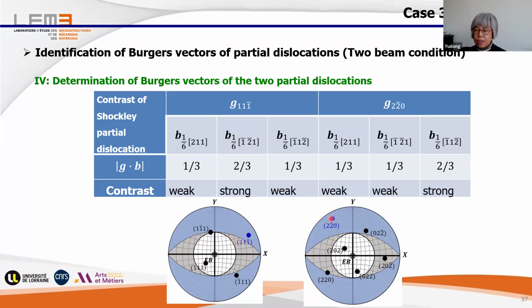And to have a 2-beam condition, the pole should in fact move towards the gray circle, because this pole corresponds to the normal vector of this plane. And so if we move it to this, the plane is parallel to the beam. Okay, and so in this case, the rotation is like this. And for this case, the rotation is like this, to reach this gray circle.